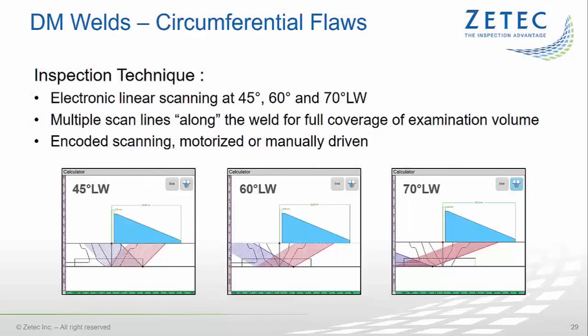If the weld crowns are ground flush, this allows for scanning of the probes on the weld surface. For detection and sizing of circumferential flaws, 1.5 MHz DMA assemblies with a large footprint can be used to generate focal laws at 45, 60, and 70-degree L waves with an adaptable primary aperture. This aperture is then electronically scanned in the axial direction to create a set of linear focal laws.